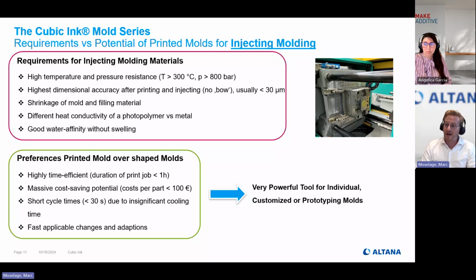Actually, the requirements for injection molding, in particular physical resistance, are pretty high. Temperatures and pressure in injection molding processes are typically very, very high. Among the standard materials used, polypropylene, polyamide, and so on, it needs a tolerance of more than 300 degrees centigrade and an injection pressure, post pressure, of circa 800 bars. It needs the highest dimensional accuracy because injection molding is usually done for really industrial parts, not for toys, basically. And the material needs to survive that.